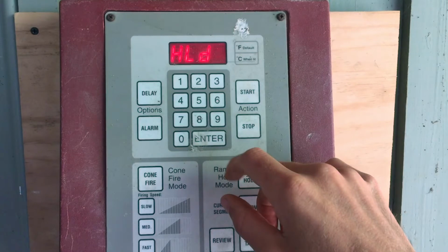Now, one super important point about the cone fire mode is that it will prompt you for a hold time at the end of your programming cycle. And the hold time is actually the time that the kiln will hold at the peak temperature. If you enter 1 hour here, it will fire up to the maximum temperature and then maintain that maximum temperature for an hour. That could cause significant glaze runs and damage to the kiln furniture. So typically we don't do any hold time at all, and it's best to just avoid this function unless you